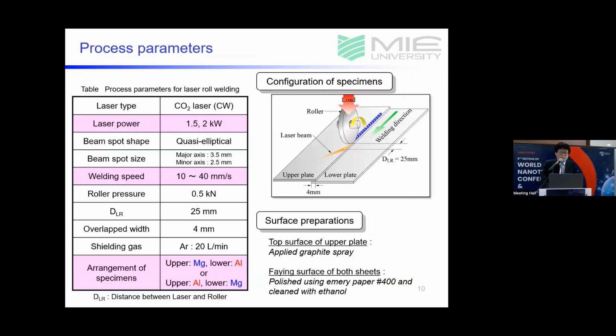This table shows process parameters of the laser welding. We used the CO2 laser, and the laser power was 1.5 and 2 kilowatt. Welding speed was varied from 10 to 40 millimeters per second. Load pressure was 0.5 kilonewton. As shown in this figure, the overlapped width was 4 millimeters. Argon gas with a flow rate of 20 liters per minute was used as shielding gas.